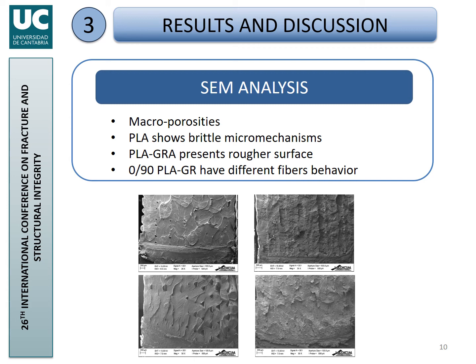So in 45/-45 raster orientation, there is a full change of fracture mechanisms, whereas for the 0/90, the change in fracture mechanisms is much more partial, with little effect on the overall macroscopic behavior.